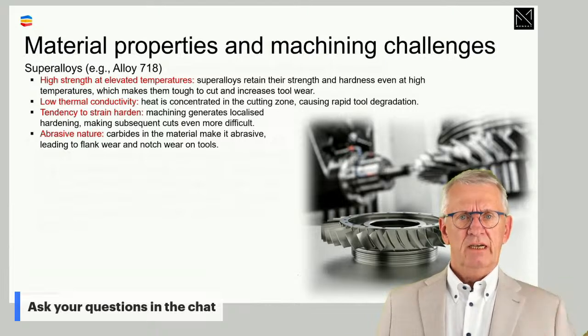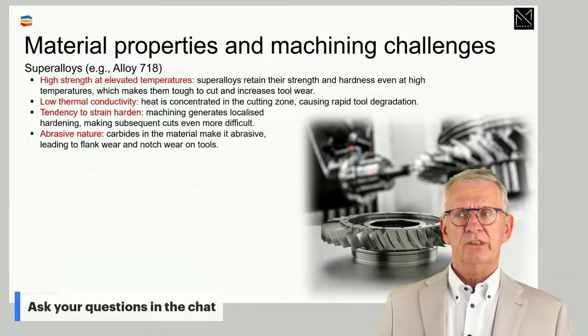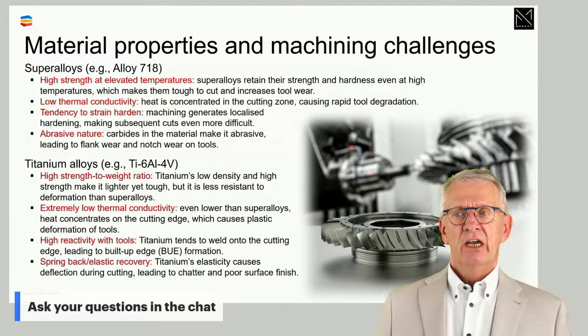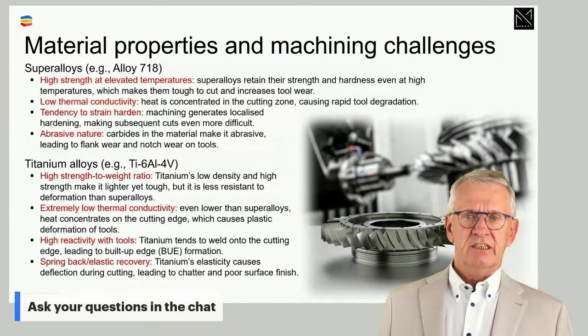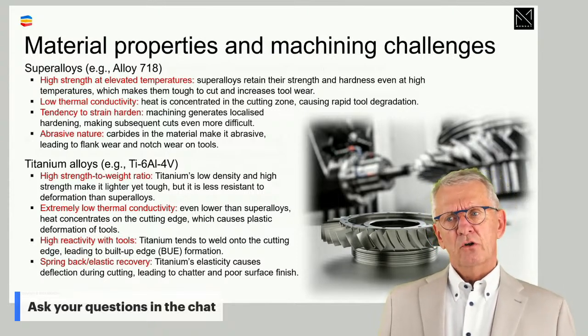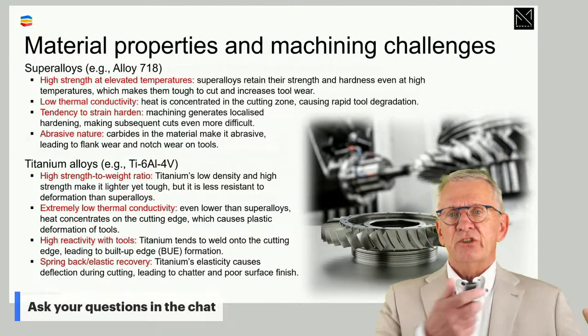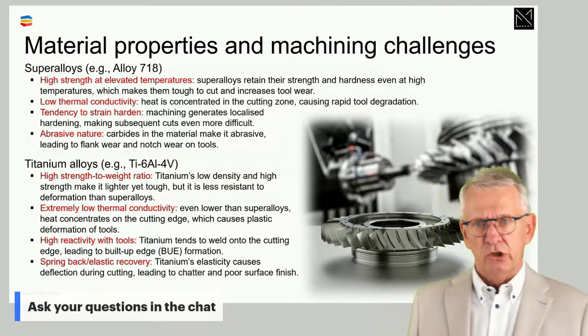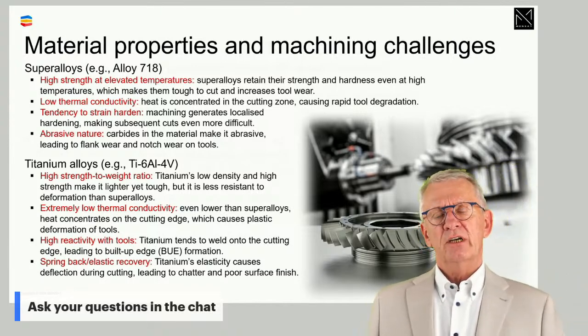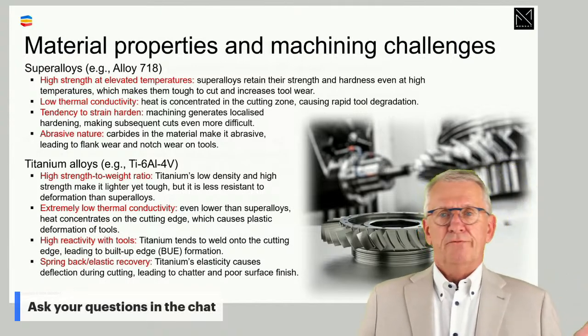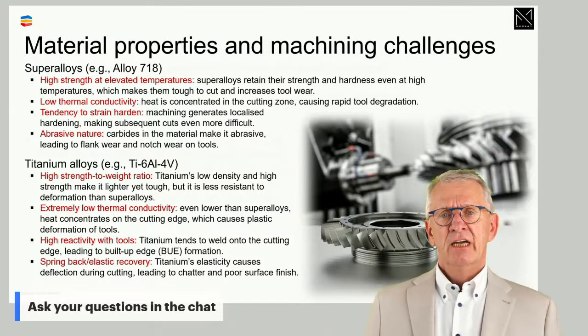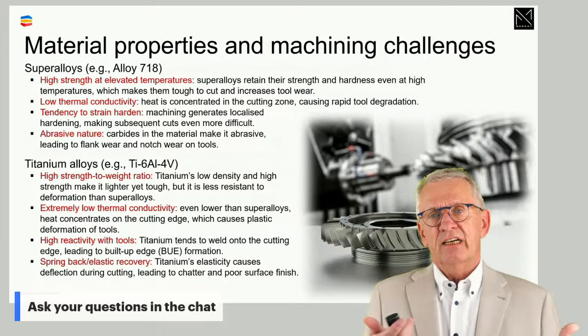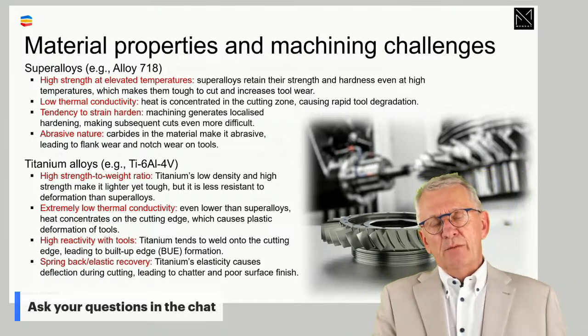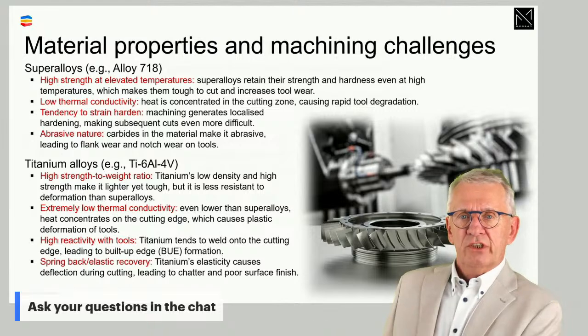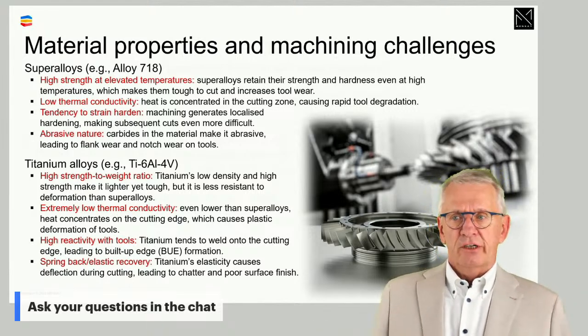Superalloys, we give you the properties and the consequences of those. If you look to titanium alloys, superalloys have high strength at elevated temperatures. Titanium is also called high strength, but it's a different high strength. It's a high strength to weight ratio. And when the temperatures stay below 400, 450 degrees Celsius, titanium kind of has a higher strength than a superalloy. But when the working temperature where the workpiece you produce is going to be used in is higher, then it's a different story.